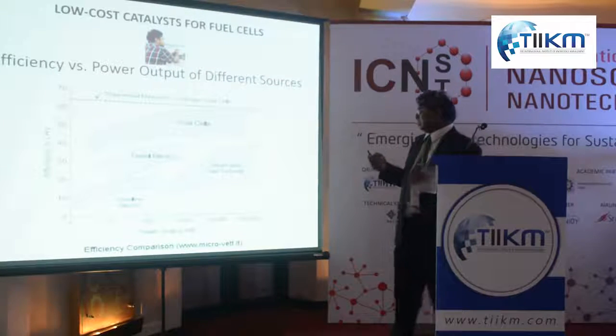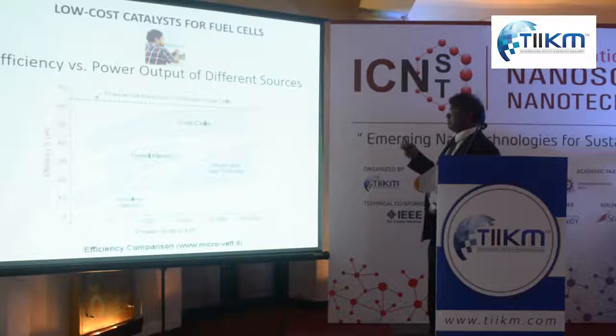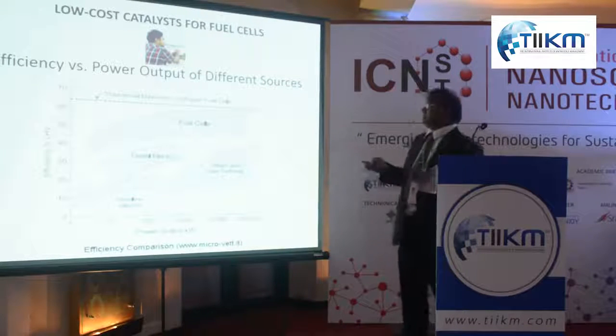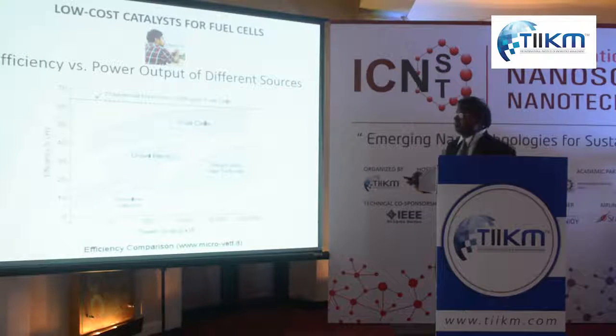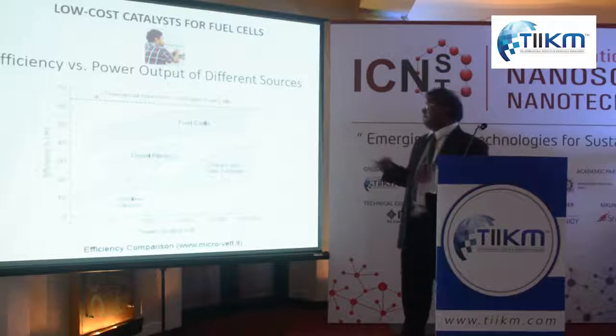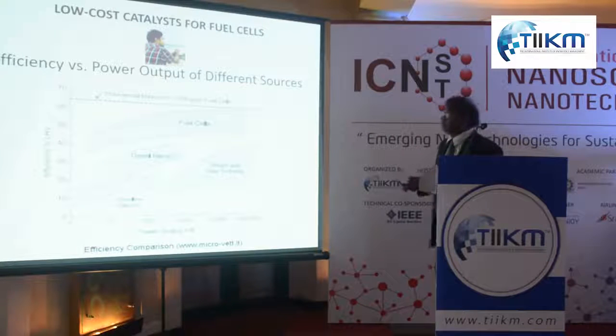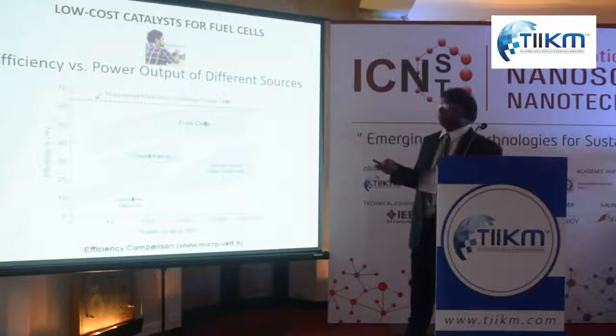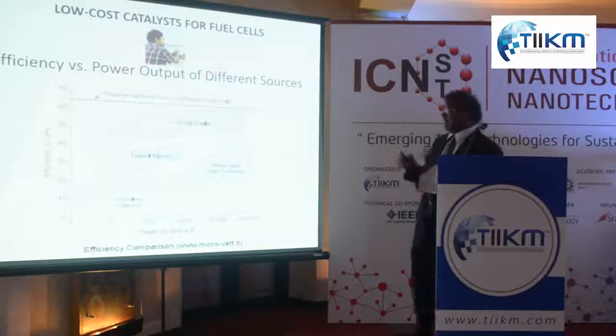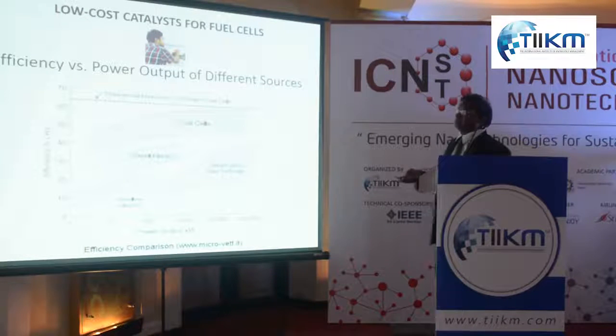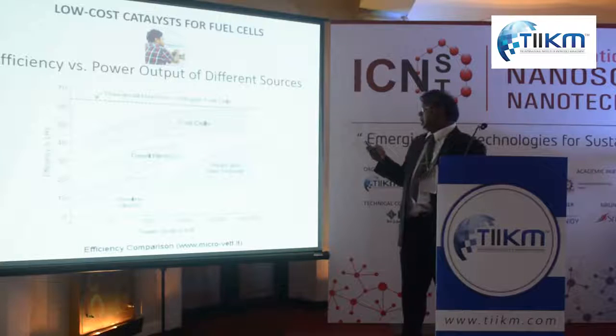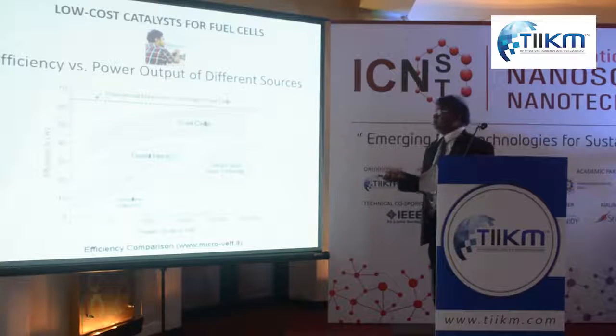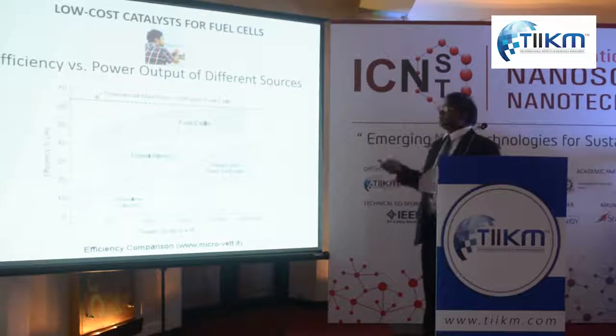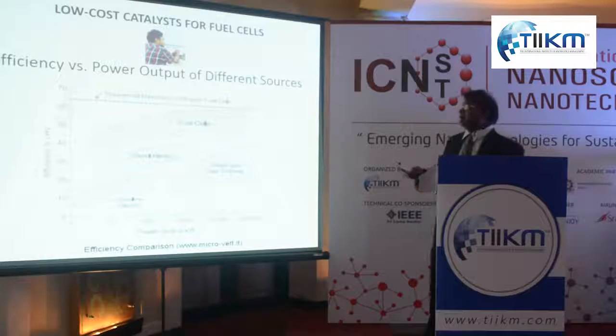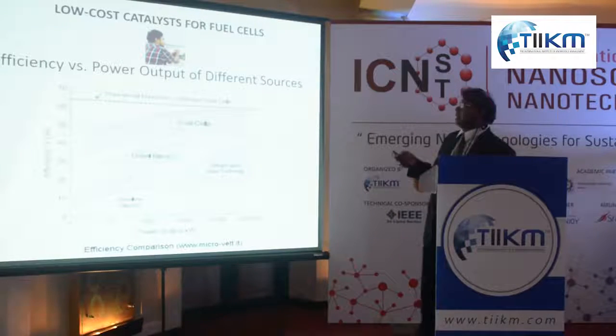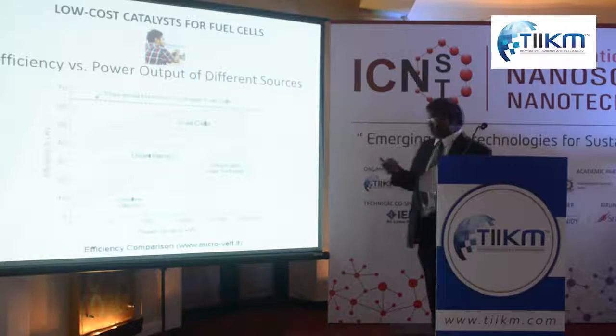So hydrogen, you see, is a very small molecule. Hydrogen oxidation is relatively easy, having about 50 millivolt overpotential over the standard electrode potential. But oxygen reduction is very difficult because it involves a large molecule, breaking a double bond and all kinds of difficult things. So it involves about 500 millivolt overpotential. So we concentrated on developing a new, low-cost catalyst instead of platinum for fuel cell applications.